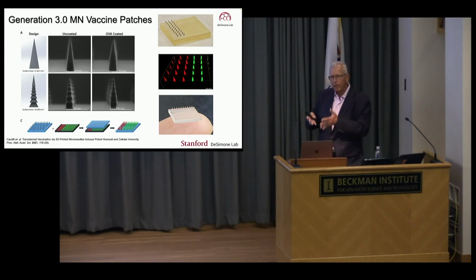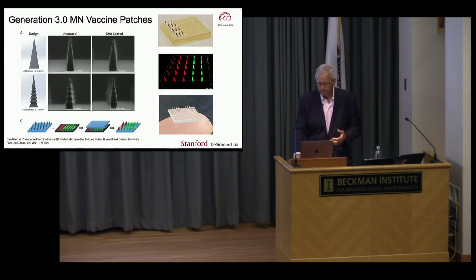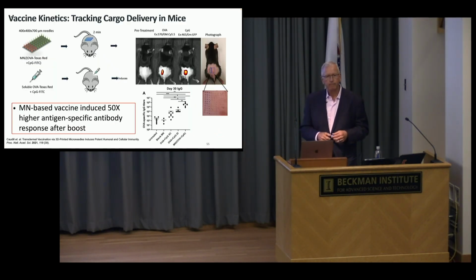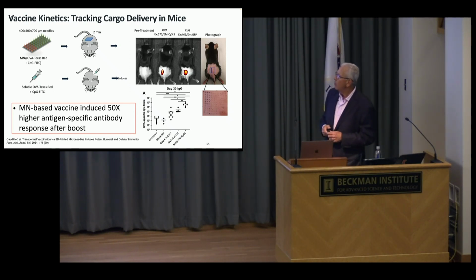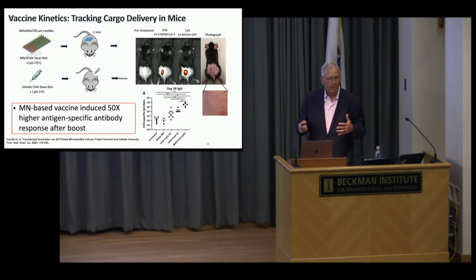The water, you dip it in, it would drain, water would evaporate, and you'd have the coating of sugar or a polymer on the needles. And then you could press this into the skin, and you could do a vaccination. And we showed a couple years ago now that we could get a 50-fold increase in antibody response, delivering the same vaccine into the dermis than you would into the muscle, just by taking advantage of the precision delivery.